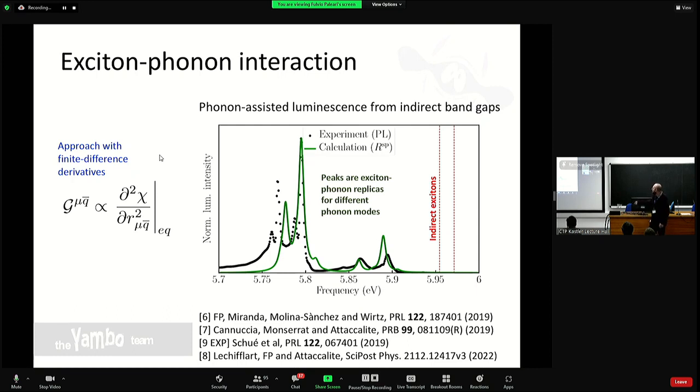So in this case, we have bulk boron nitride, and the photoluminescence signal, actually this is cathodoluminescence signal, is determined by the emission, the recombination basically of some excitons at finite momentum, and they can only recombine emitting light via the help of a phonon, of several phonon modes.